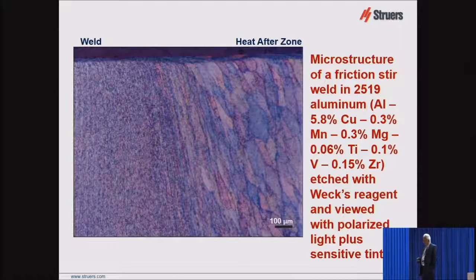This is a friction stir weld in 2519 aluminum. And here's the composition here. We're etching this with a color etch developed by Erich Weck. Erich died a few years ago. He had retired 15, 20 years ago, was living in the Canary Islands when she died. But he developed a very nice etch for aluminum and a very nice color etch for titanium also. And here's the mark that the stirring device makes in generating the heat for friction stir welding. And this is the weld metal over here, and this is the heat affected zone after the weld, and we're at 100x.